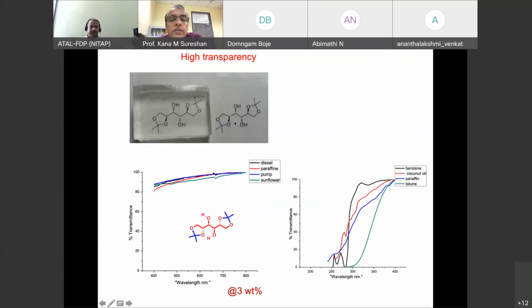So this gelator, if you make gel out of this in paraffin oil, this is a 5 centimeter thick gel block. This is the structure of the gelator. Both are identical structures, chemical structures. On one of them, I have placed a 5 centimeter thick gel block made out of the same material and paraffin oil. You can see both the structures very easily.